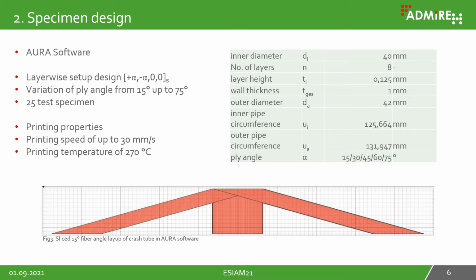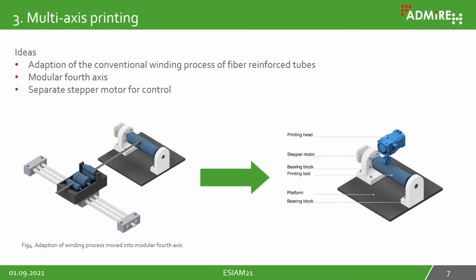So we chose 270 degrees Celsius of printing temperature and a printing speed up to 30 millimeters per second. In figure 3, you can see a sliced 15-degree fiber angle layup of a crash tube specimen in the Aura software. The idea of our multi-axis printing is the adaptation of the conventional winding process of fiber-reinforced tubes. We wanted to build a modular fourth axis with a separate stepper motor for control.